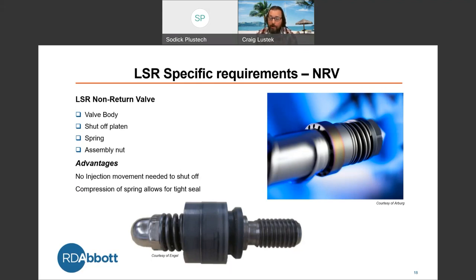You can run LSR without a spring loaded non-return valve, but sometimes you have to give it a quick hit on your injection profile to be able to shut that platen onto the body. And sometimes that can hinder your process depending on if you're micro molding or the type of part you're manufacturing. If it's a thin wall, you could streak into that part. So the best is to always utilize for liquid silicone rubber that spring-loaded non-return valve.